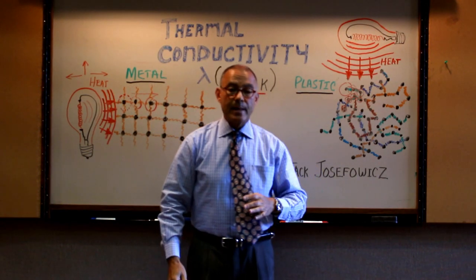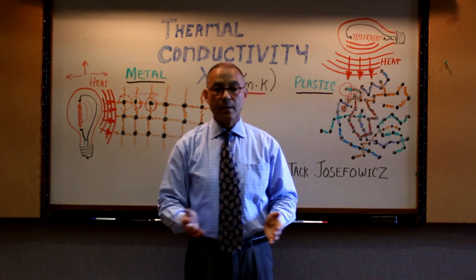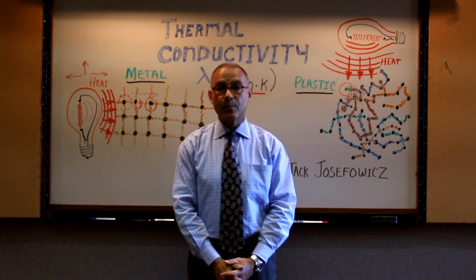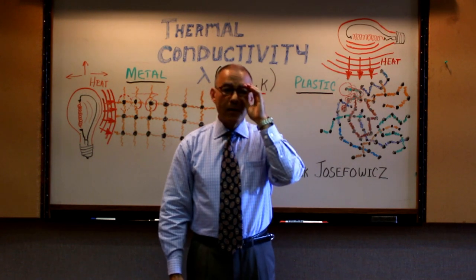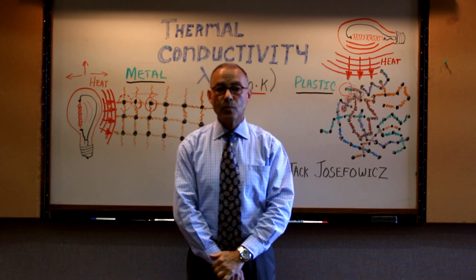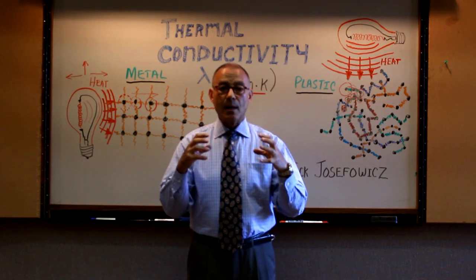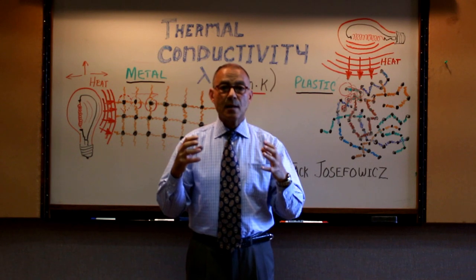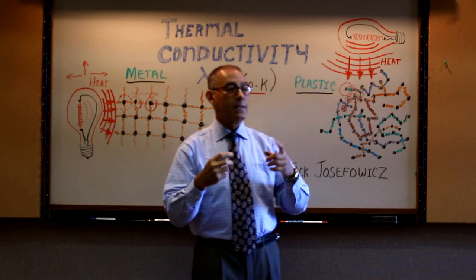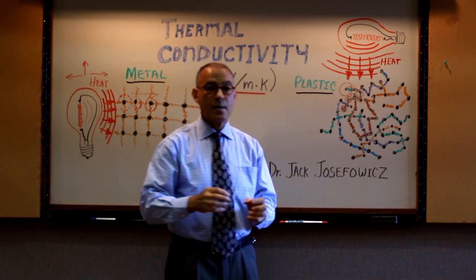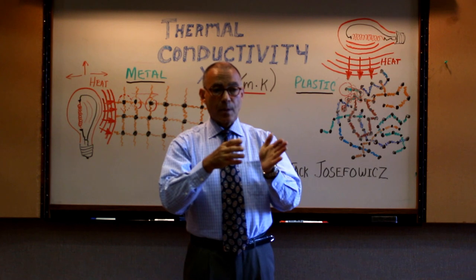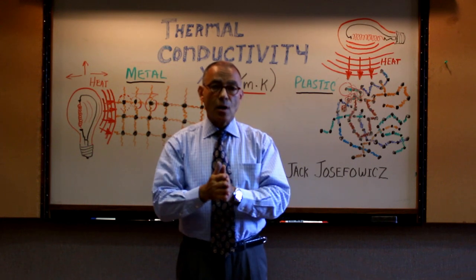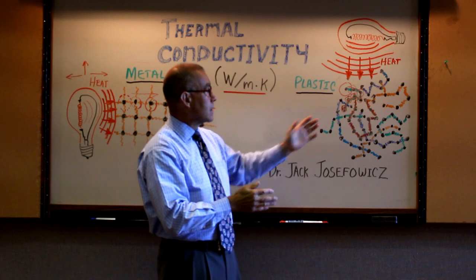In the area of aerospace and electronics reliability, the rule of thumb is that for every 10 degrees increase in operating temperature, you have a 50% reduction in reliability. So a lot of effort in material science is going into surrounding electronics with different kinds of organic materials that have special kind of fillers like ceramics, which produce a higher thermal conductivity in a plastic when you embed ceramics in it, so that that material can bleed the thermal energy away from the components and lower their operating temperature. So there's a lot of research going on, especially in organic chemistry, for this purpose.